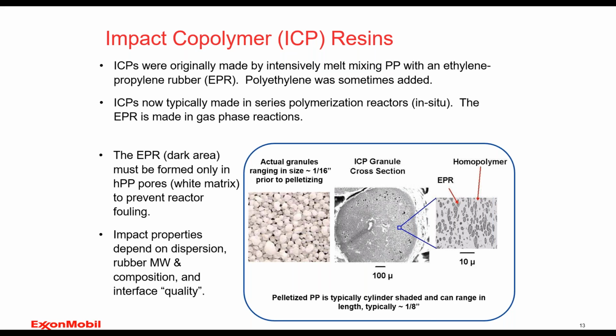And in that time frame, they would mechanically blend modifiers in. And since then, in the early 1980s, like 1982, they first came up with reactor grade ICPs, which are typically made in a series of polymerization reactors or in situ, one right after another. And that's what ExxonMobil produces today in many locations, our Baytown facility and our Singapore facility. These impact copolymers start off by making a homopolymer that is designed for additional blending. If we look in the picture here on the left side, we see pictures of actual granules. These granules are small, certainly less than 1/16 of an inch.